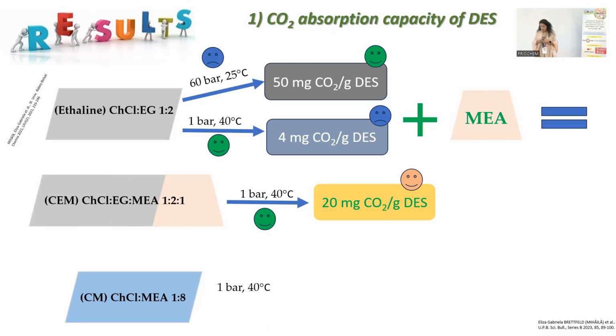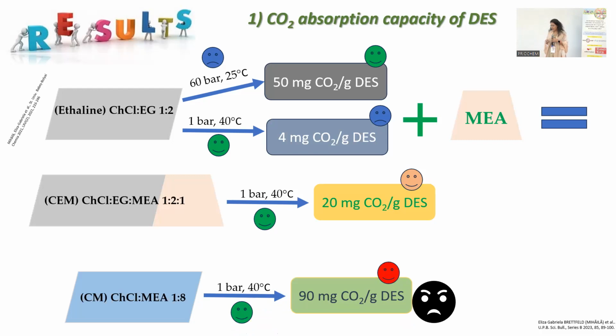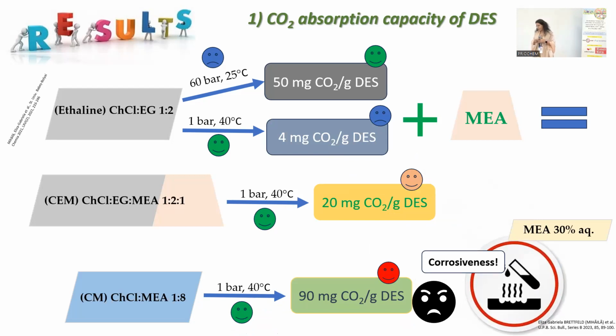Another solvent I studied was a binary one, but exclusively with monoethanolamine and choline chloride. From several optimizations, this molar ratio was the optimum. We had a very good absorption result, but this isn't a really big surprise because we had a high amount of monoethanolamine, which in time will cause some problems, just like the classic method with aqueous monoethanolamine solution, because it has high volatility and corrosiveness.